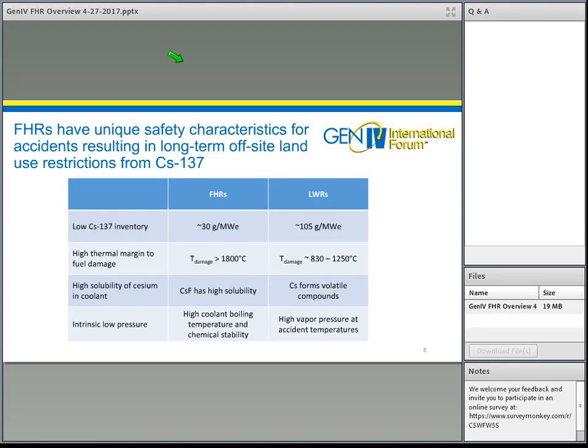The third major attribute is the fact that cesium, when it's in the chemical form of cesium fluoride, which it will take in the salt in FHRs, has very high solubility and very low volatility, particularly when we compare it to the chemical forms that cesium takes in water-cooled reactors under accident conditions, where cesium and iodine both take volatile forms and therefore can be mobilized in the form of aerosols.